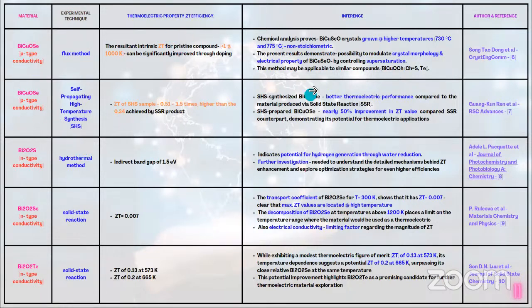Inference. Based on the available data, this slide suggests that bismuth copper oxide selenide is a promising candidate with the potential for high thermoelectric figure of merit values. However, this potential is highly dependent on the specific synthesis technique employed. Bismuth copper oxide chalcogenides and bismuth oxide chalcogenide type materials exhibit various types of conductivity, followed by various experimental techniques, that is flux method, self-propagating high temperature synthesis, hydrothermal synthesis, and so on. The experimental technique relies on the thermoelectric properties, ZT efficiency, and how the inferences are referred.